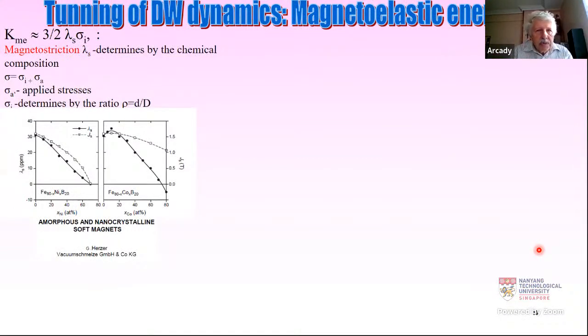Here I will show you the possibilities to tune the domain wall dynamics of our materials. So first, an important contribution which affects magnetic properties of amorphous materials is magnetoelastic energy, and it depends mostly on two parameters: magnetostriction and internal stress. Magnetostriction can be tuned mostly by the composition. So these are iron-nickel and iron-cobalt systems. We are interested in positive magnetostriction because of the relationship between hysteresis loop and the composition. And so we can tune the magnetoelastic energy by changing the chemical composition also.